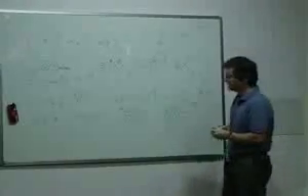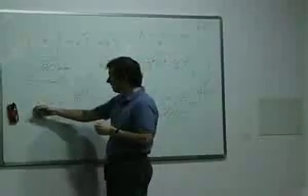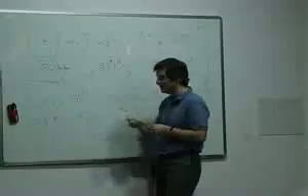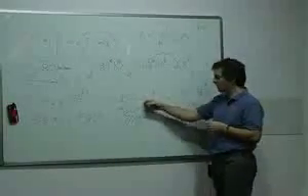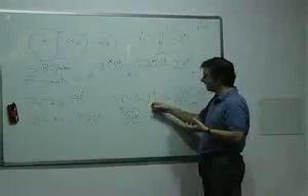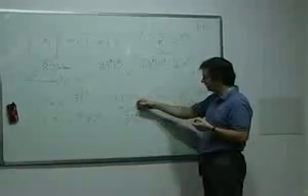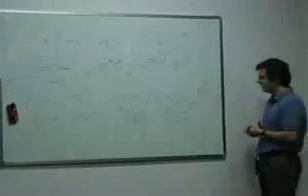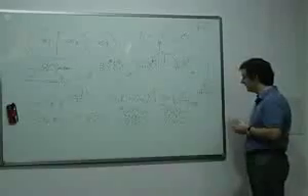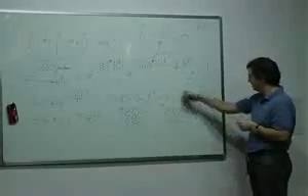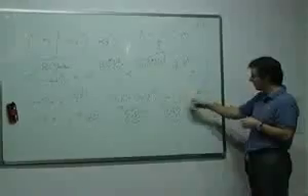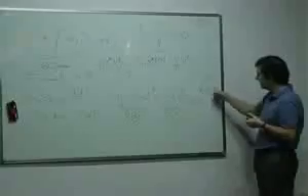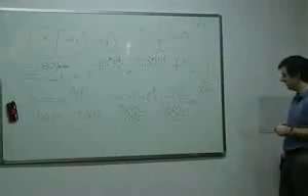And then to get the time scale, we say that the time scale will be a microscopic time scale times an Arrhenius factor with a barrier, and the barrier scales in this way. It's a kind of activated dynamic scaling, in which there is a prefactor, delta 0, and then the length to some power psi. Again, just for generality, I put a general exponent psi. This gives you a time scale which is a function of 1 over the configurational entropy, like you have in Adam-Gibbs, but here you have a general exponent, psi divided by d minus theta.